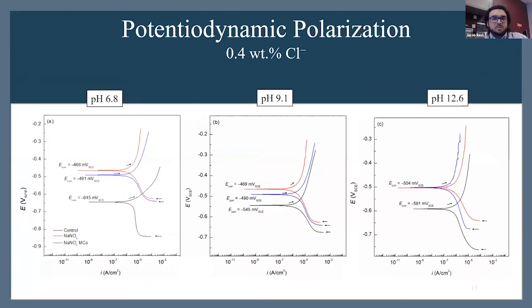In terms of the most important part, with the polarization studies and the EIS studies to show the effectiveness of the microcapsules, they were exposed for 7 days in the different pH solutions to allow for sufficient inhibitor to be able to see a major inhibition effect. And what we see is from left to right, we have our low to high pH, and in blue, we have all of our microcapsules. Red are the free sodium nitrite inhibitors, non-encapsulated in the same system, and our black is our control, all in a low chloride, 0.4 weight % chloride solution, as the maximum, widely held maximum allowed amount of chloride in the concrete mortar or matrix.